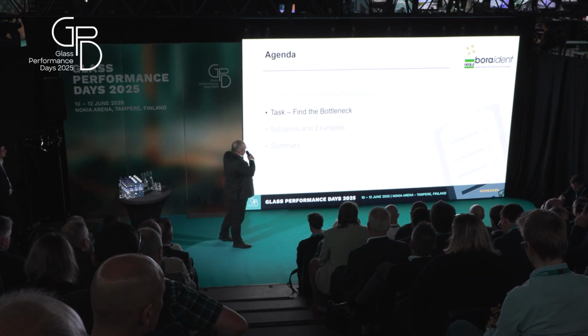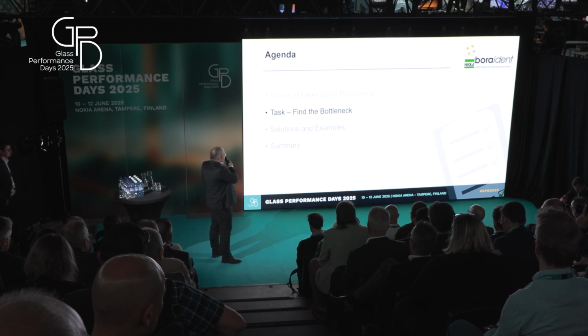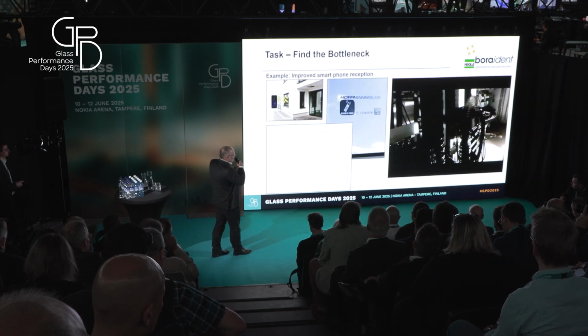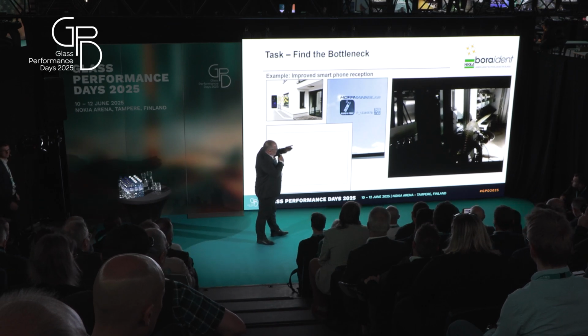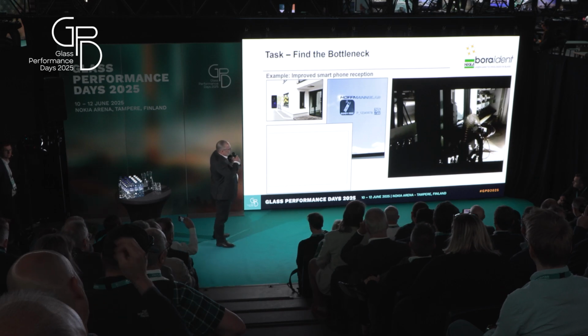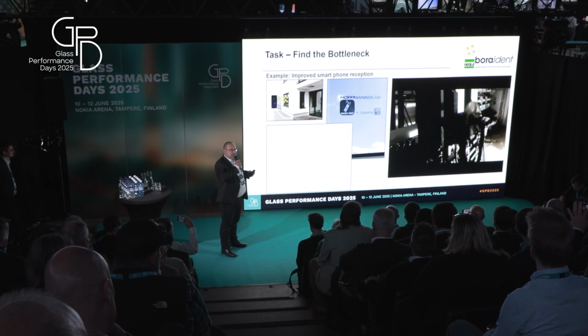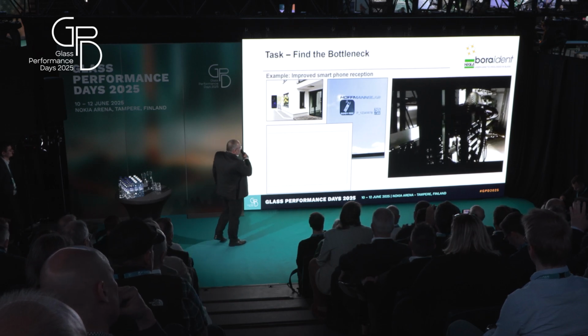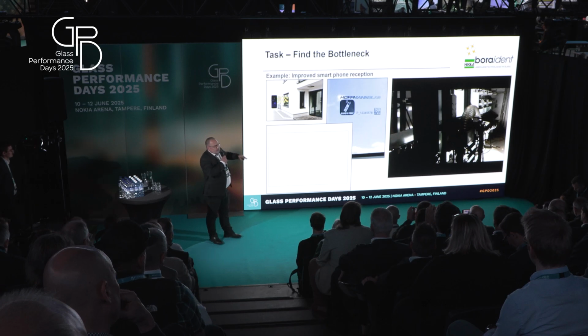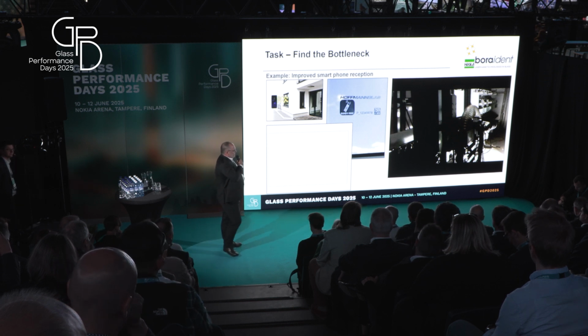And the question is why it is there. If you have a little bit of a closer view to the laser process here, you see an example of structuring low-E coating. On the right-hand side, you see the laser forms some patterns, and these patterns in a low-E coating remove the low-E coating to have then a better access by smartphone inside concrete steel buildings with modern high-performance windows. And you see the laser do this circle by circle, each after each other, and this leads to this process time pieces per minute.